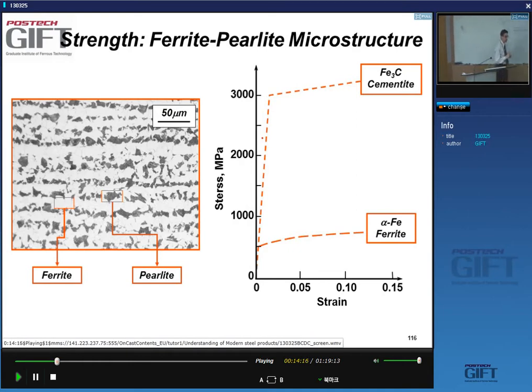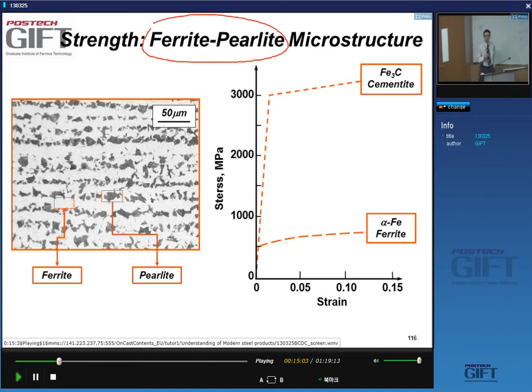but traditionally, in very many standard commercial steels, what we use as a strengthening mechanism is basically carbon, yes? We don't use carbon as a solute. We use carbon in the form of cementite, yes? And in fact, the carbon itself is present as cementite in pearlite. So if we look at the standard commercial so-called ferrite pearlite steel, what we see in the microstructure is this. You see this black phase, which is pearlite, and these white grains, which are ferrite, yes?